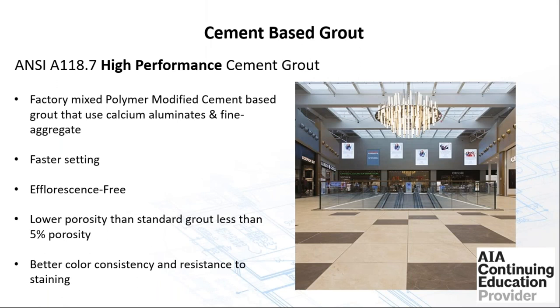118.7, this is your high performance cement grout, calcium aluminate mixed with fine aggregates. A lot of advantages to this product. It's faster setting, efflorescence free, because again, it's not a Portland-based cement product. Lower porosity. I mean, we talked initially, way back in time, 35% absorption, then we went to 18% porosity, 10% for the standard 118.6, and now we're talking a lower porosity and 5%. That makes a huge difference in an installation. So obviously with that, you're going to get better color consistency and resistance to staining.